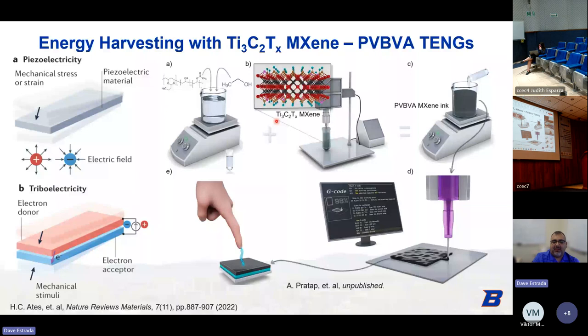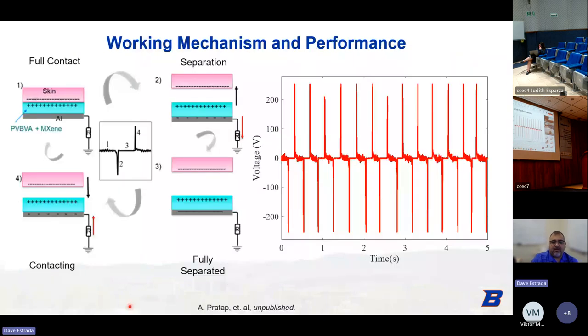And if we add enough MXenes, enough PVBVA, we get a nice viscous ink, which is compatible with extrusion printing. And we can print that directly on an electron acceptor layer, or we're using aluminum foils for that. And so if you're not familiar with things, our working mechanism is something like this, right?